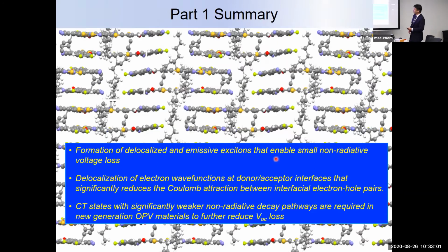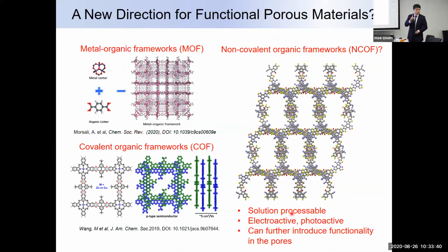Okay. So here is a very short summary. With this very interesting, right, organization of the molecule, we can form very delocalized and also emissive exciton, enable very small non-radiative loss, right? And also the delocalization of the wave function, right, at the donor-acceptor interface also helps us to reduce the Coulombic interaction of the charge transfer exciton. It also helps to reduce, right, the energy required to separate it, so making it a very highly efficient material. And here is also one possible direction, right, to work on this new type of organic semiconductor.